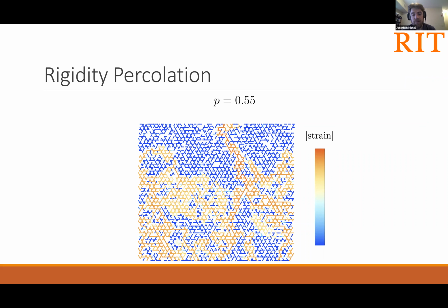Right, that's just it. So our idea was that the vertices in this network correspond with places in which adjacent fibers in the collagen scaffold and the tissue are cross-linked chemically to one another. And to our knowledge, the Kagome lattice gives a more appropriate distribution of valences than some of the more highly coordinated alternatives.